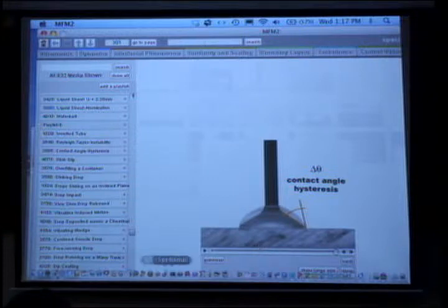And so you can ask, what's the origin of this? We've just used a simple energetic argument to say that there should be an equilibrium angle, but there isn't. What's actually happening is the following. Our idealized picture is that the contact line moves on a perfectly flat substrate, but in reality there are always roughness elements. As the contact line advances, it gets snagged on roughness elements and impurities, so there can be junk down on the surface, either chemical impurities or texture.